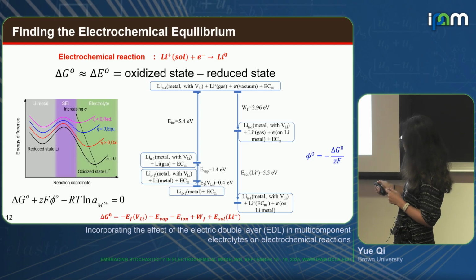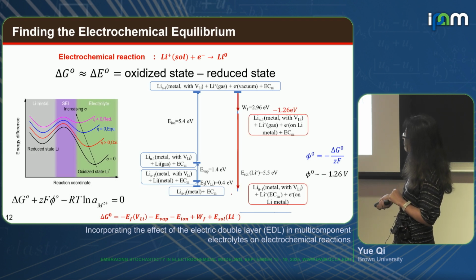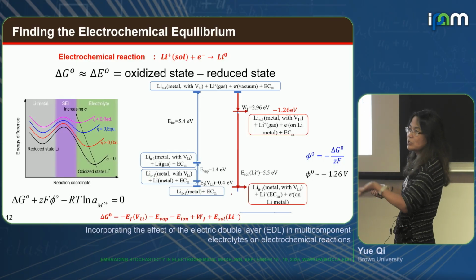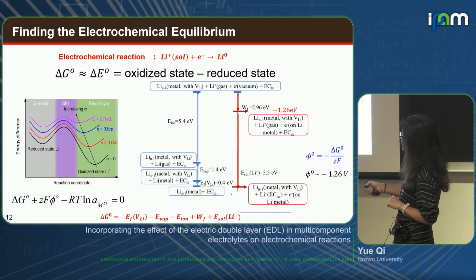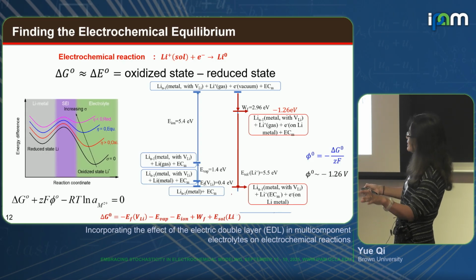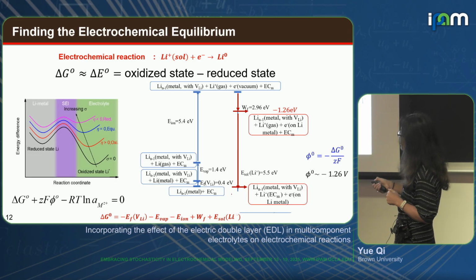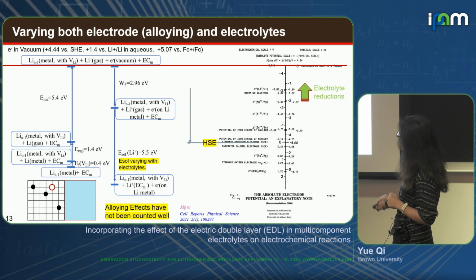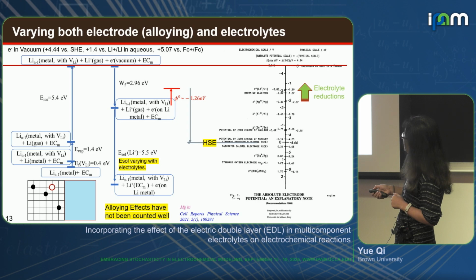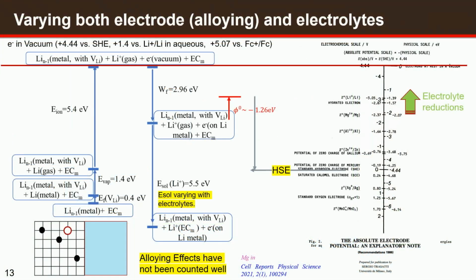So that means this is delta G0. I hope this notation is right. And with the first level of approximation, we have to shift this electric potential up on the metals, lift the Fermi level, so we can make the lithium ion's energy level in the liquid phase and the lithium metal in the solid phase at the same level. This is electrochemical equilibrium, and then my electrons are already here. And this actually gave me this nice relationship.